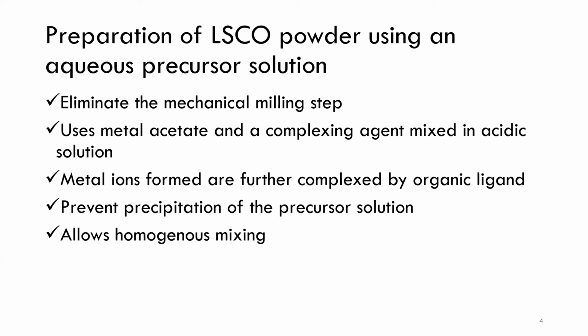In this study, a simple route is investigated for the preparation of LSCO powder using an aqueous precursor solution. In this method, we eliminate the mechanical milling step that is done in the conventional solid-state reaction method. This method uses metal acetate and a complexing agent mixed in an acidic solution in order to eliminate the need to perform mechanical mixing. Metal acetates, when mixed in acidic solutions, are converted into metal ions. Metal ions are then complexed by an organic ligand, which prevents precipitation of the precursor solution and allows homogeneous mixing of the precursor solution.